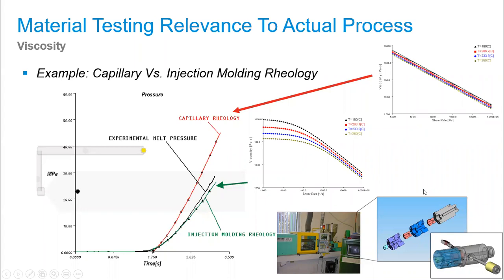And we see a couple of viscosity curves from a straight capillary rheometer, where we've modified the temperatures, took it through the die, and we're getting a very linear power law type of response on this particular material. But when we use the same material and take it through an injection molding rheometer, we get a similar function at the very high shear rates, actually a little bit different. So if you actually draw the line over, we are a little bit higher on the scale, because we just can't get to these high shear rates, so we have to interpolate these based on the slope of the curve over, which is why we feel it is more accurate.